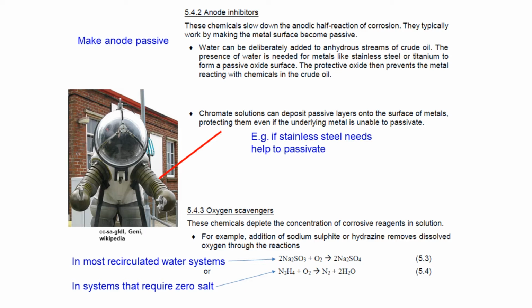We could use inert gas sparging, bubble pure nitrogen through the liquid. We could use some sort of vacuum treatment to try and remove dissolved gases. Something that we do quite often in a recirculated water system is we would add chemical oxygen scavengers. Sodium sulfite, for example, will sponge up oxygen as per reaction 5.3. And in another case, we might use reaction 5.4.